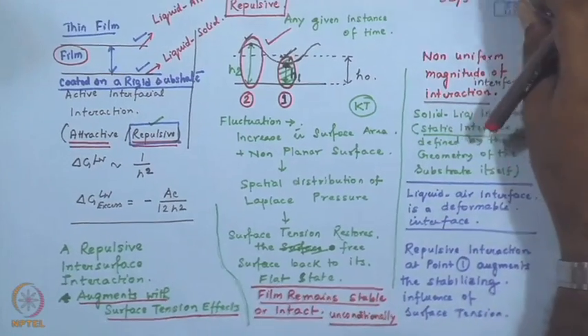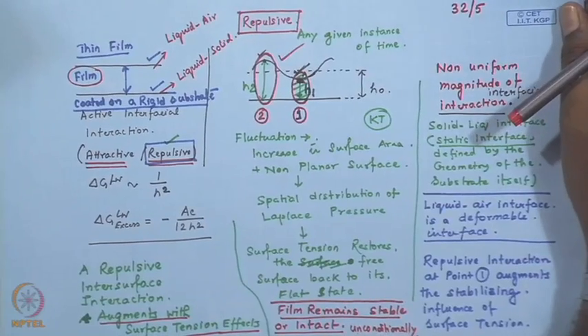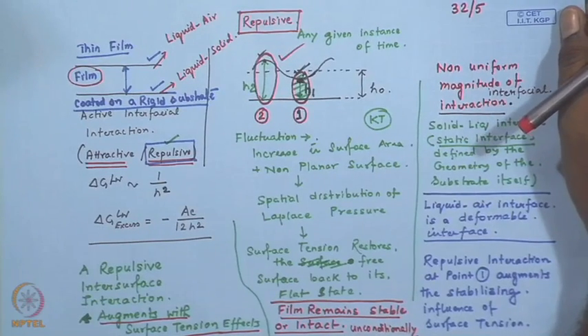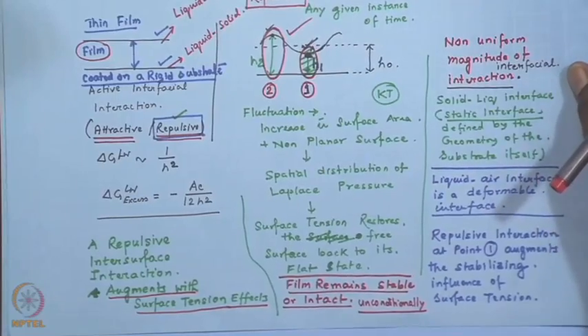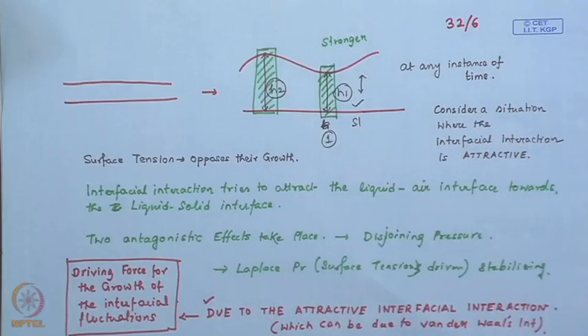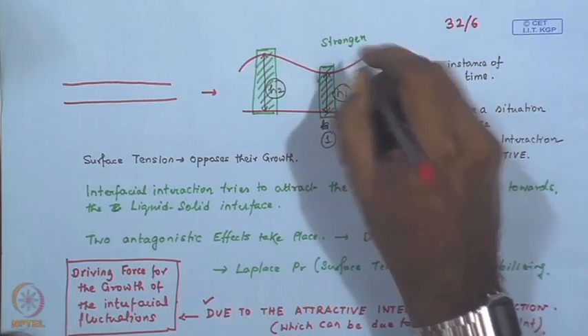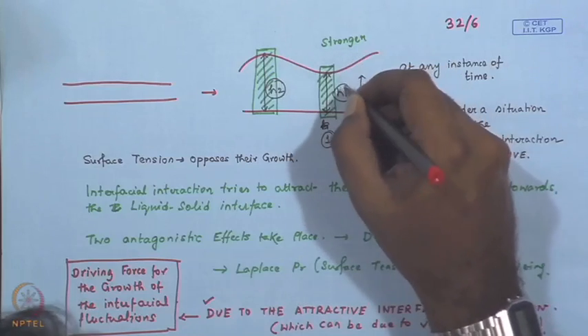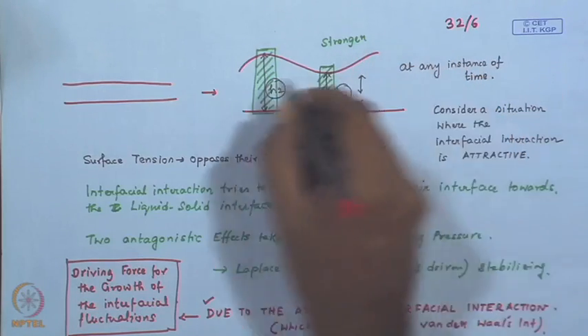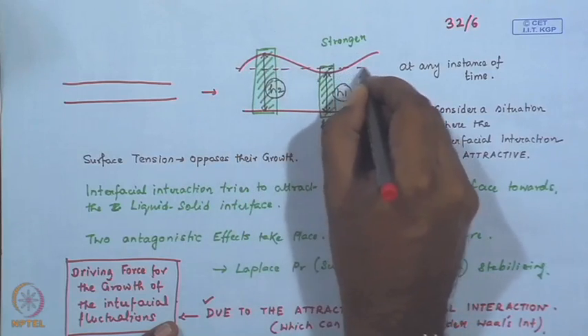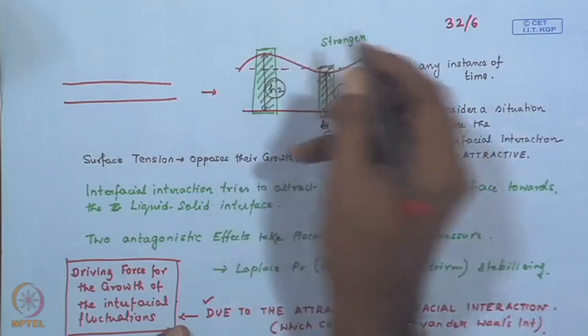Okay. So, this is what happens if you have a very thin film with an interfacial interaction which is repulsive in nature. In contrast, if you have a scenario where the interaction is now attractive, then over a zone which corresponds to a valley of any instantaneous fluctuation, the two interfaces are now closer as compared to a peak of the surface fluctuation.